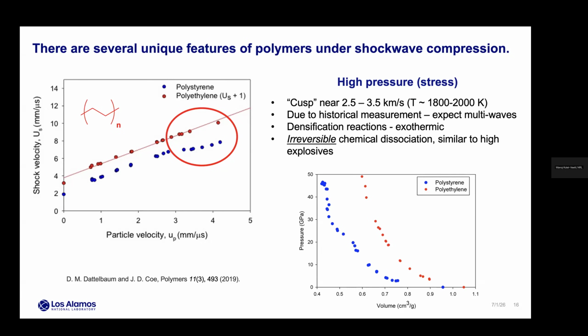So, Los Alamos, yeah. Are you at any point during the shock forming graphitic sort of structures, or if you go to high pressures, are you going to a diamond-like structure? Yeah. So the way that we model it currently in our codes, which is too simplistic, is that if we're above 25 GPa, then we assume that all the carbon goes into the diamond phase. We've already shown with some of our light source experiments that that's not the case. It turns out to be a mixture.